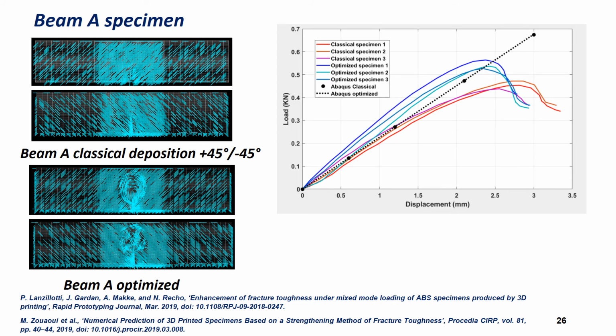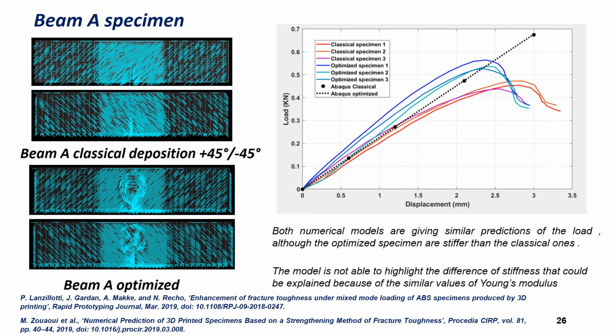As we can see from the graph, both numerical models are giving similar predictions of the load, although the optimized specimens are stiffer than the classical ones. The model is for the moment not able to highlight the difference of stiffness, which could be explained by the almost isotropic elastic behavior.